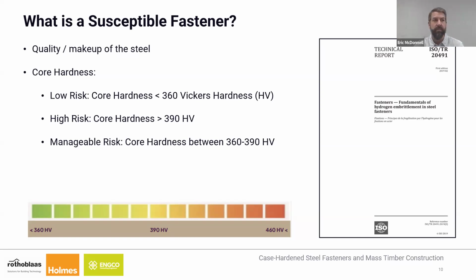And what's been outlined in this ISO technical report is really that if you have a hardness below 360, the risk of hydrogen embrittlement is pretty low, not eliminated, but certainly much lower. When you're above 390, it's shown that the risk starts to get quite elevated and increase pretty quickly. And in between 360 and 390, it's considered to be manageable if the right precautions are taken, which we'll outline from the tech report.